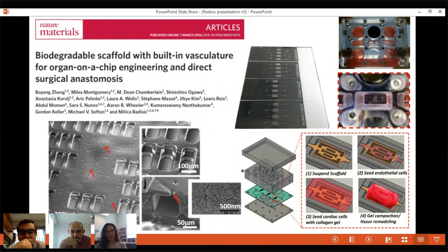The first step in this procedure is endothelializing the channel lumens, and that usually takes about 24 to 48 hours. You can inject basically the endothelial cell suspension from both sides of the lumen, and they will be drawn into the lumen, into this branching vasculature by capillary action. And so if you wait for 24 to 48 hours under gentle rocking, you will be able to endothelialize fully this scaffold.